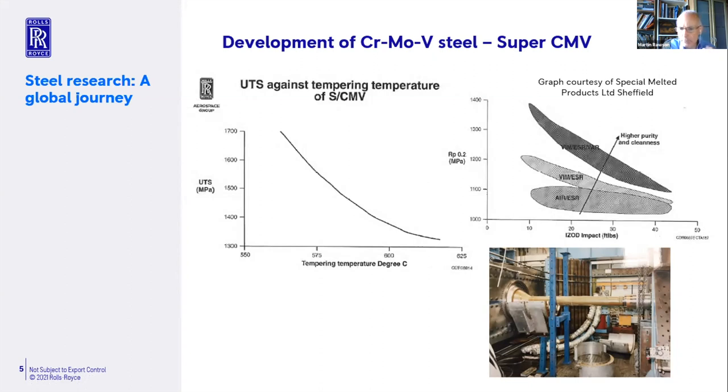That's the story of SuperCMV: taking an existing chromoly vanadium steel — 3% chrome, 0.5% molybdenum, 0.2% vanadium, around 0.4% carbon — and making it fit for purpose by controlling the melt route. Like any new material, we had to test it before putting it in the engine. The picture shows one of our turbine shafts undergoing torsional testing. The machine applies a major torque load equivalent to a takeoff event, an axial load, a fluctuating vibrational torsional load, and a rotating bending load — quite a complex load cycle.